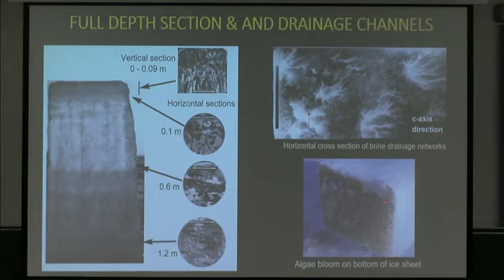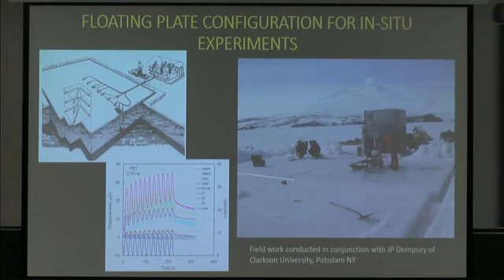But we do look at the crystal structure down through the sheet in addition to looking at the flaw structure and the salinity profiles. Give you a little idea of what our field experiments look like. This is a nice little drawing. We cut a sheet of some size, a few meters up to 10 to 20 to 30 meters. My colleague John Dempsey has done up to 80 meters on a side.